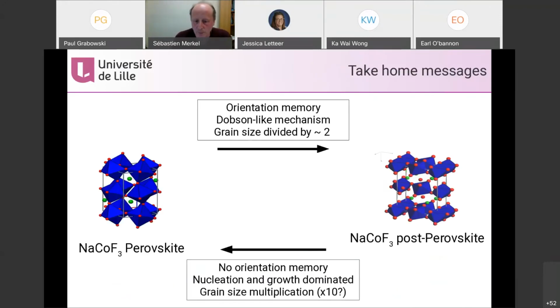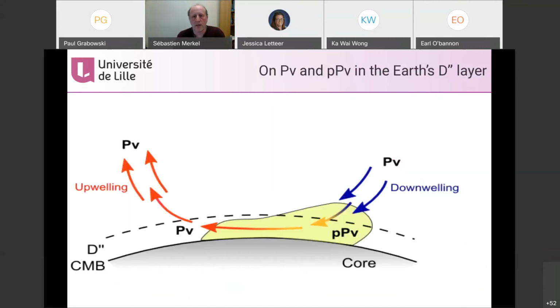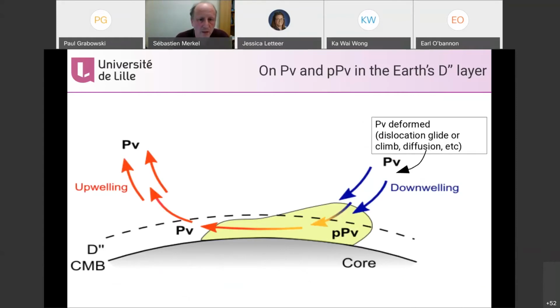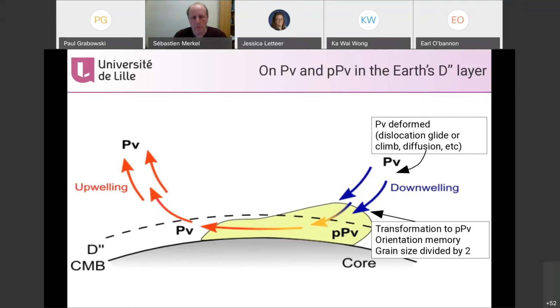So what are the consequences of that? If you are talking in terms of geosciences, you imagine you have a downwelling slab that goes down in the lower mantle. You'll have deformation of your perovskite polycrystals through dislocation glide, dislocation climb, diffusion, whatever. You'll be building a microstructure in perovskite as your material is going down in the Earth's mantle. As you make post-perovskite, you'll get a transformation to post-perovskite, and you will keep a memory of the microstructure in perovskite. It will be changed, but there'll be a memory, and the grain size divided by 2.